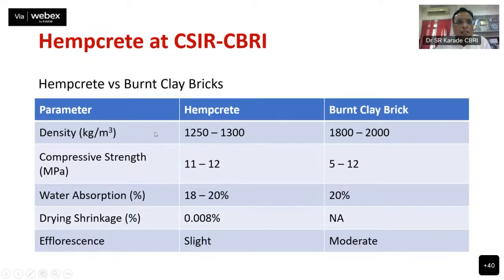With the geopolymer, we could achieve a density of 1250 to 1300 kg per cubic meter and 11 to 12 MPa strength. Water absorption is below 20%. Shrinkage is also very less. There is a slight efflorescence. In comparison to burnt bricks, you can see here, we are getting better properties.